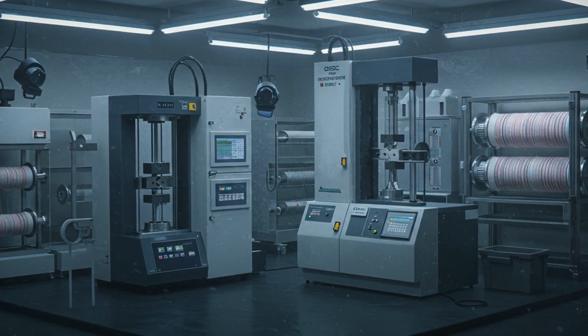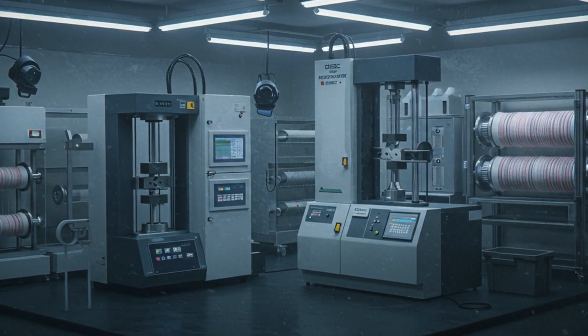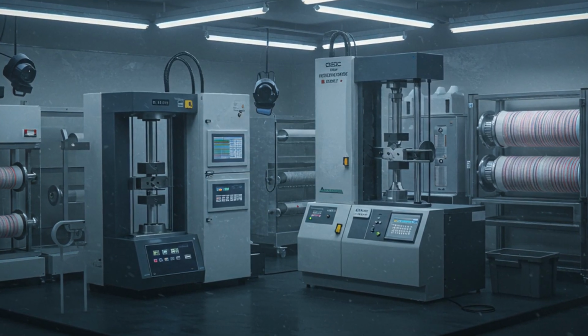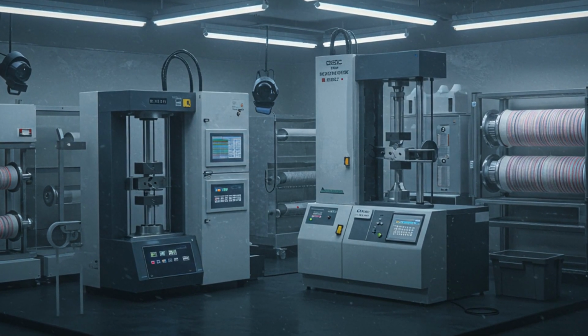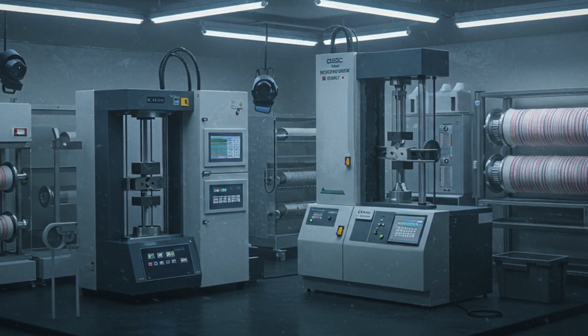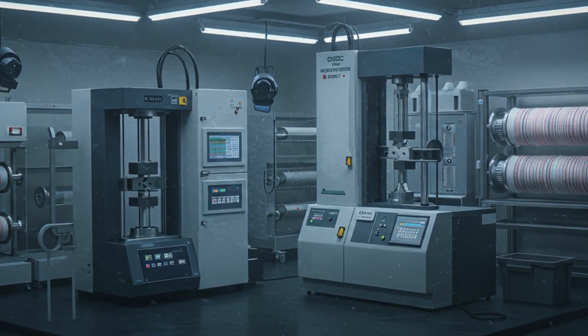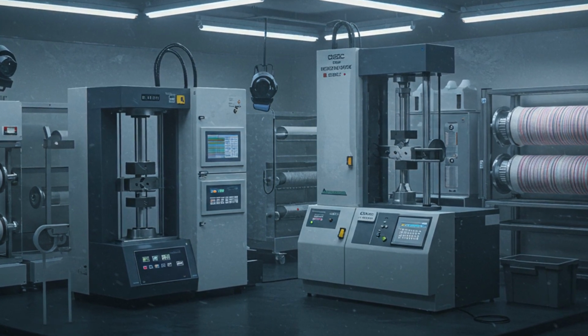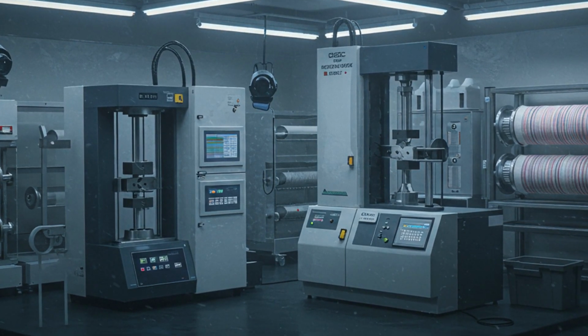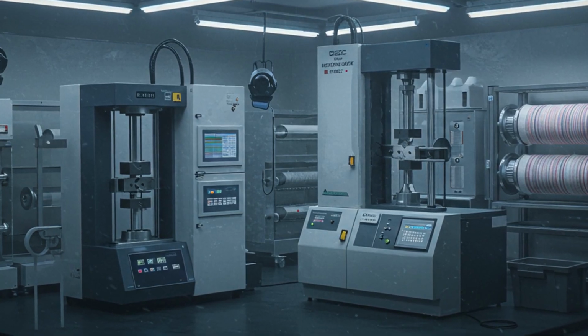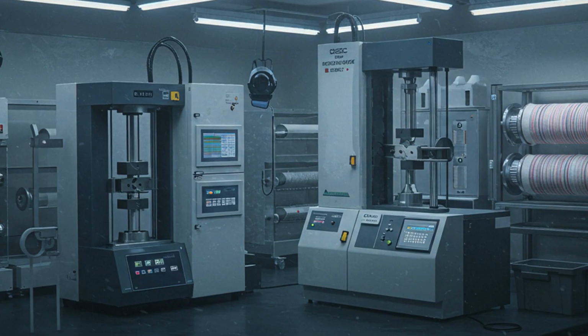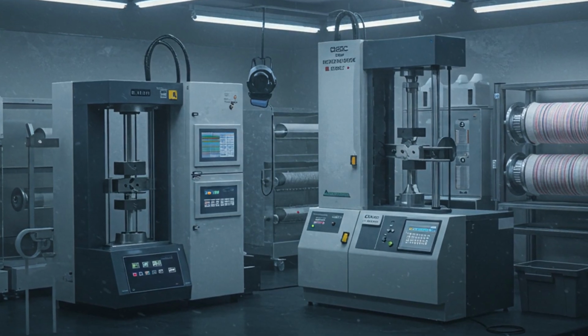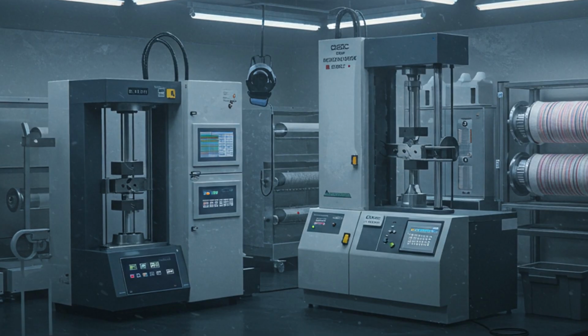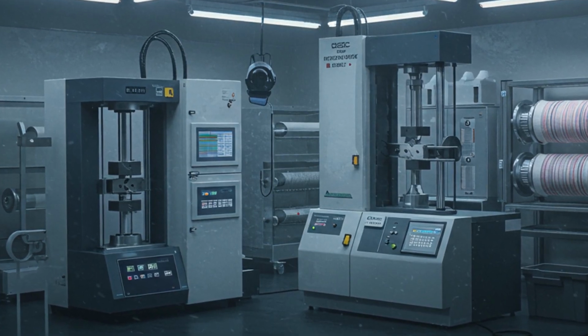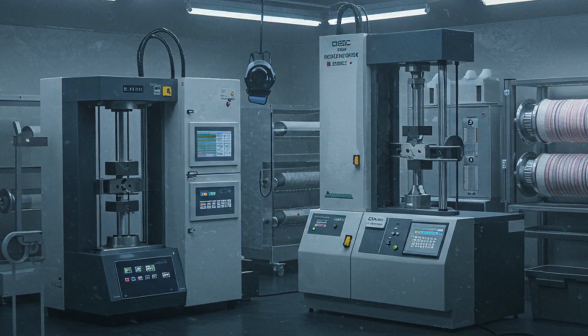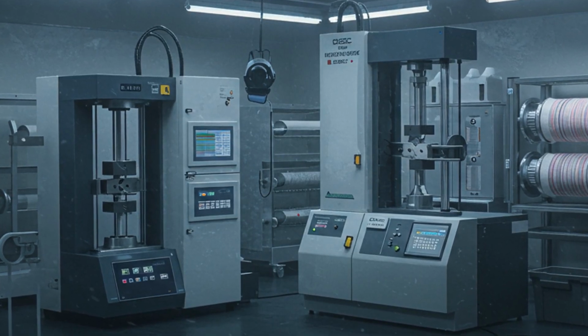Thermal analysis identifies melting point and glass transition, while differential scanning calorimetry measures crystallinity. Color fastness labs run wash, light, and perspiration tests to measure dye stability. Abrasion testers simulate repeated rubbing, and aging chambers expose samples to UV light and elevated temperature for accelerated life tests. Chemical analysis, like Fourier transform infrared spectroscopy, confirms polymer identity and detects contaminants. Every failed sample informs process adjustments, tighter drying, different draw ratios, or spinneret maintenance. The goal is repeatability. Produce millions of meters of fabric with predictable hand, strength, and color, batch after batch.